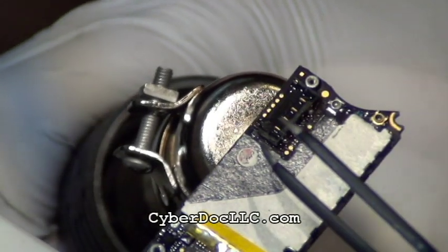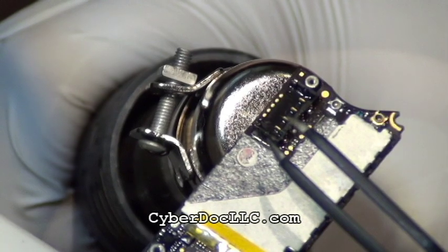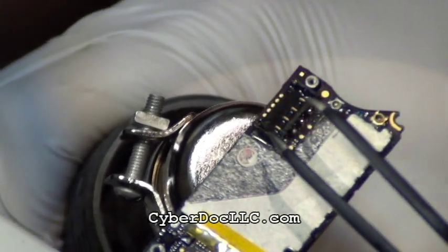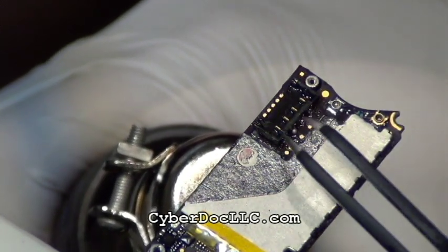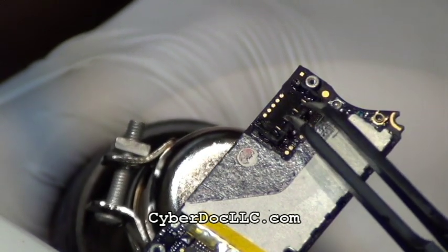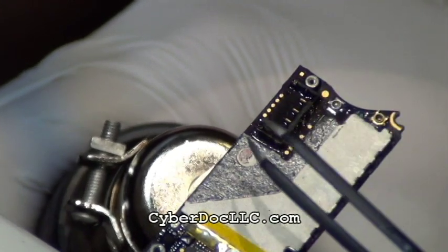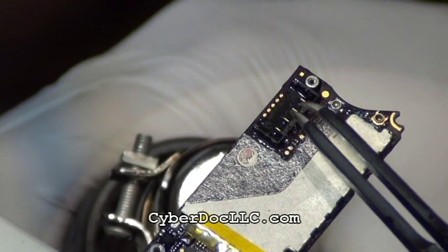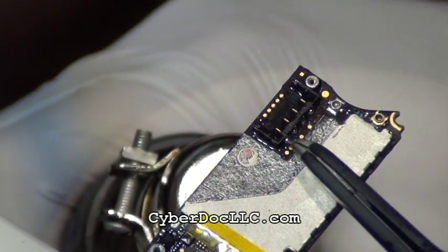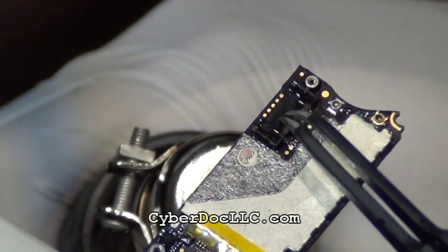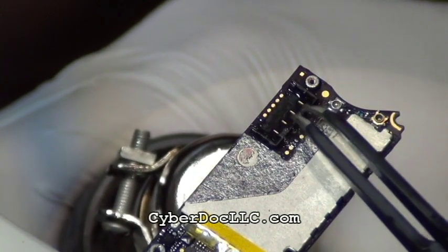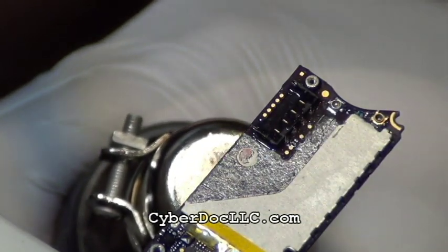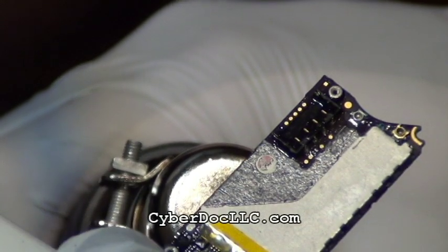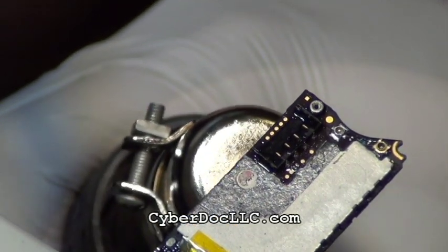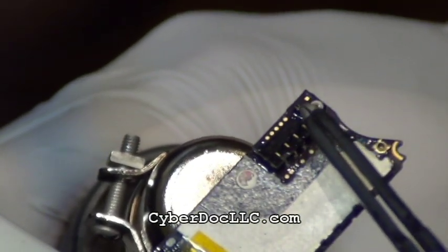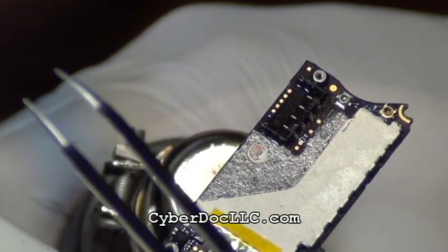Smoke means the flux, not smoke from the components. Also, the back of the logic board is nothing but a giant heatsink, and that itself is going to protect all the components from the other side, so you can heat up as much as you want. It's very unlikely for you to damage anything from the back, as long as there's a heatsink on it. Even without the heatsink, when they reflow this logic board, they do it by machine with a controlled heat profile of at least 300 degrees Celsius, roughly. So this logic board is designed to be soldered at 300 degrees Celsius without damaging the components. They usually design the components to be at least 10 degrees higher than that, maybe 20 or 30, so they don't damage it by accident during reflow.